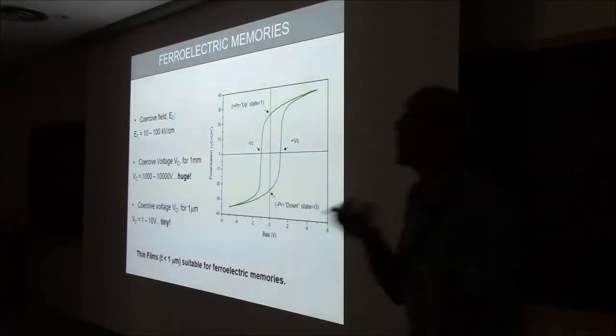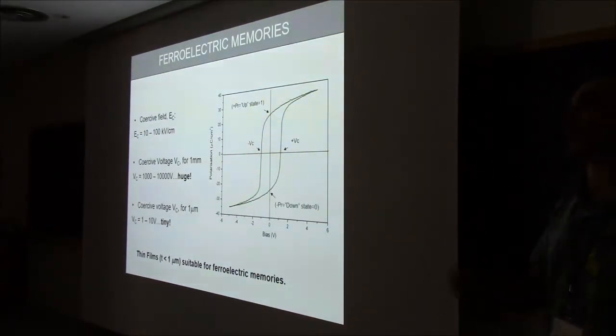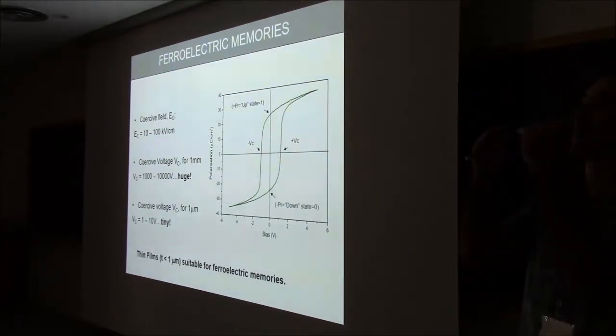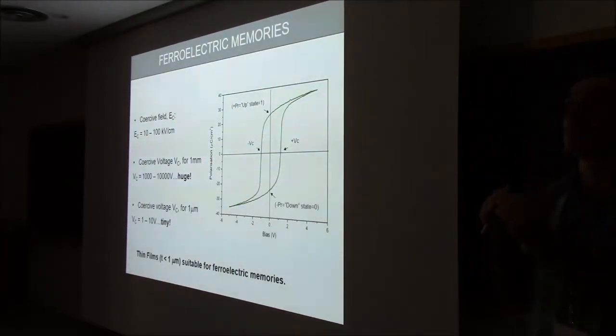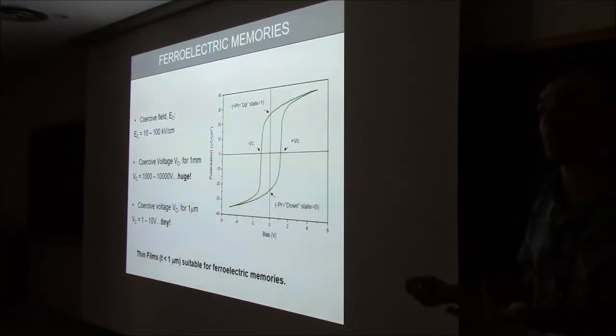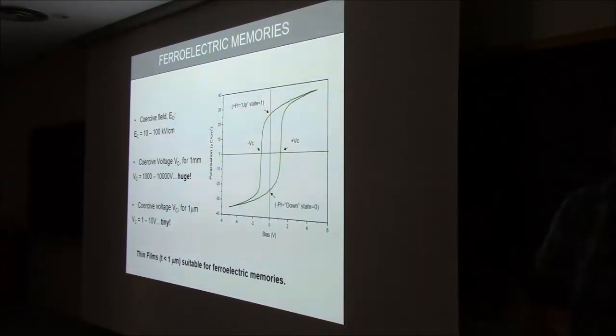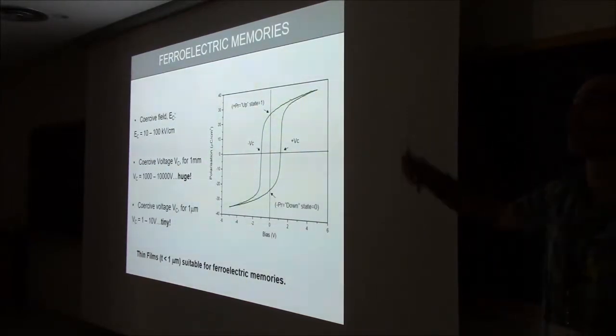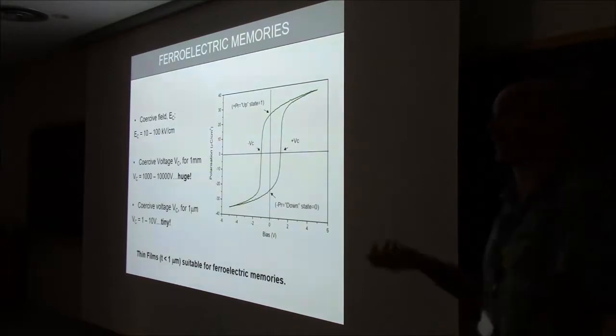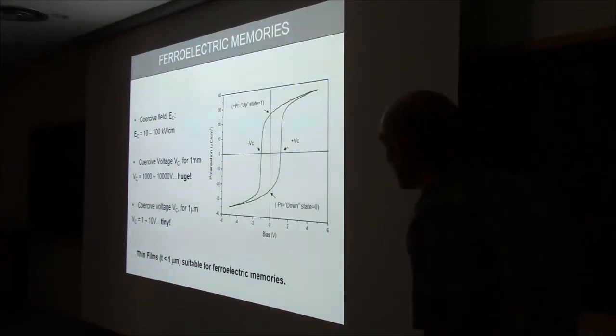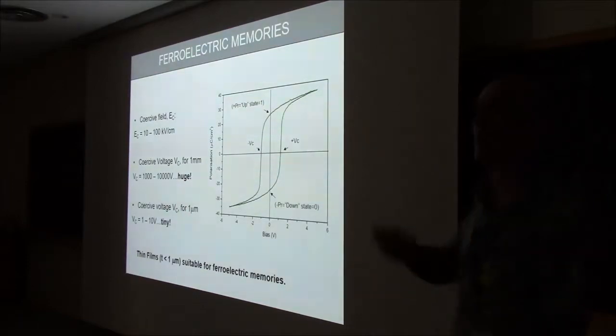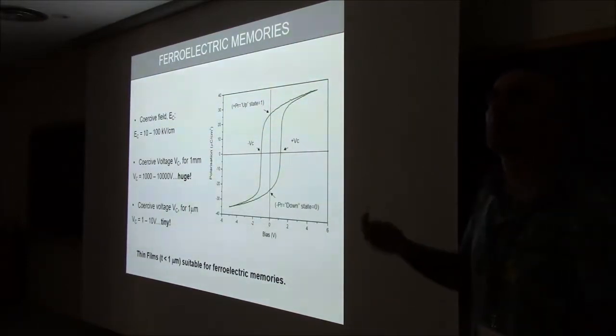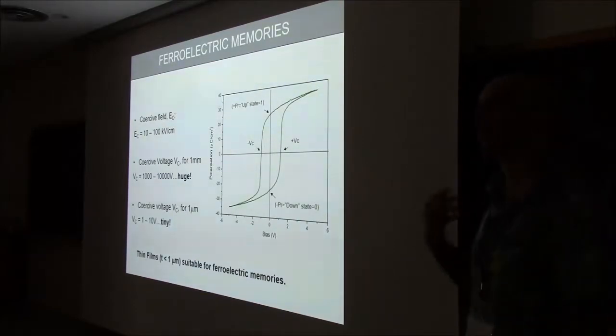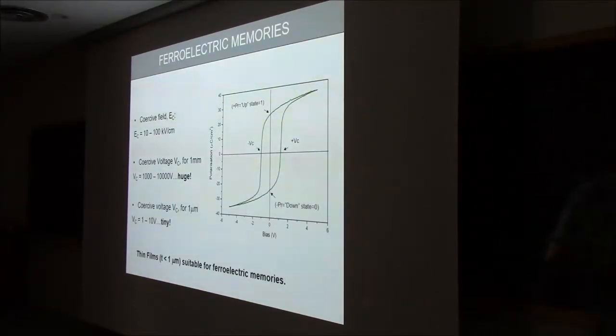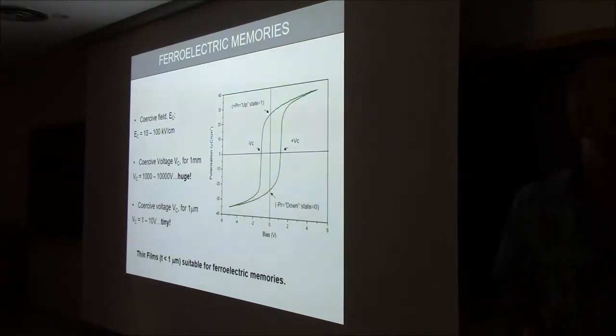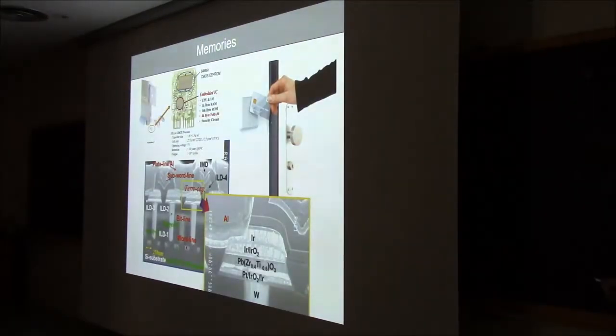However, electric field is voltage divided by thickness. So if you make your ferroelectric, instead of being a bulk single crystal, be a thin film, you need a much smaller voltage to achieve the same high electric field. Because the thickness is in the denominator, you make the denominator small, the electric field becomes big, and that's free. It's a very, very neat geometrical trick. So the coercive voltage for a film that is less than a micron thickness is typically less than 10 volts, something that you can achieve with a battery. And that's why ferroelectric memories can be useful, and are useful. In fact, ferroelectric memories do exist.